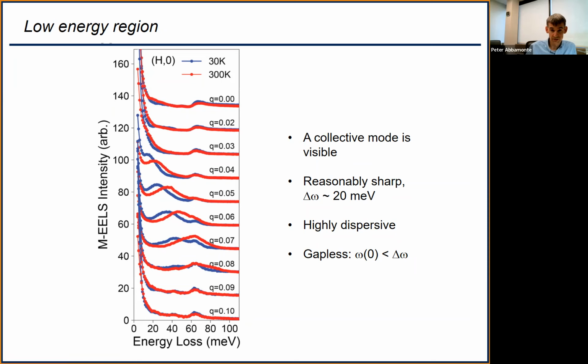So there is another collective mode in there. It's sharp, but not as sharp as a phonon. It's extremely dispersive. And as far as we can tell, it's gapless. And the dispersion curve is temperature dependent. I'll discuss that a little bit at the end. But the main thing is it does look like there's another mode there, and it's a gapless mode.